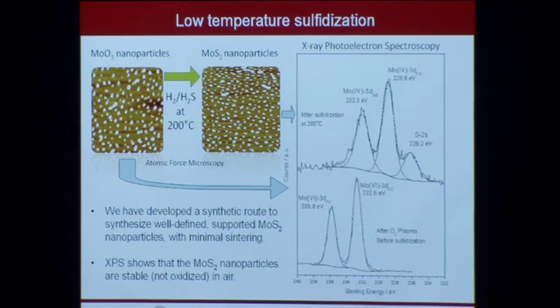After sulfidization, we asked ourselves the question, well, yes, you might form the sulfide in the furnace, but what happens when you pull it out and expose it to air? Because air is pretty oxidizing. Oxygen, in other words, is a strong oxidant. And we're a little bit concerned that these nanoparticles might be oxidized right at the edge. But the XPS, which is a very surface-sensitive technique, tells us that that's not happening whatsoever. This is a characteristic, right on the money, Mo4+ sulfide. You can see the sulfur 2s peak also emerge, and we don't see any signal whatsoever coming from MoO3 as we had seen previously. So this is very convincing that we've made MoS2 nanoparticles. Our images tell us that they're discrete and they're not getting oxidized in the air.